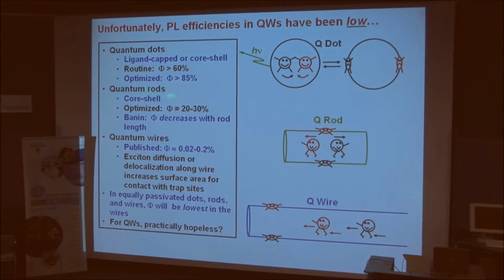What about the case for quantum rods, which are just elongated dots? There, the optimized PL efficiencies are on the order of 20 to 30%, which is still really excellent, but it's about half of that for dots. There are various arguments to describe why these are smaller, but my opinion is simply that a rod has a larger surface area than a dot. And therefore, there's a higher probability that there will be a trap site, or more than one trap site, that the carriers can encounter. And because of that, those efficiencies will go down.